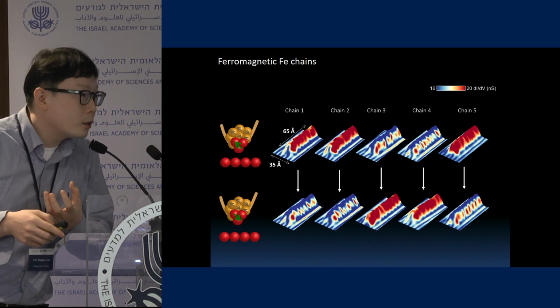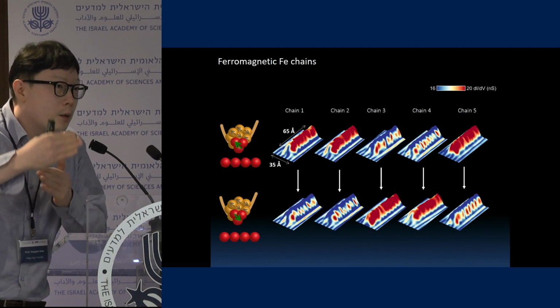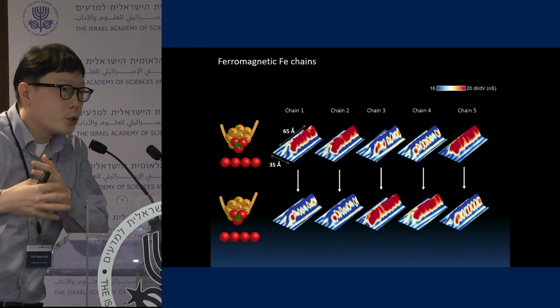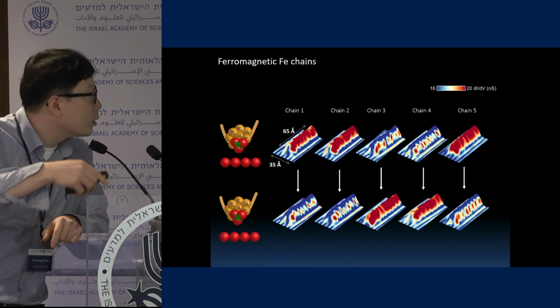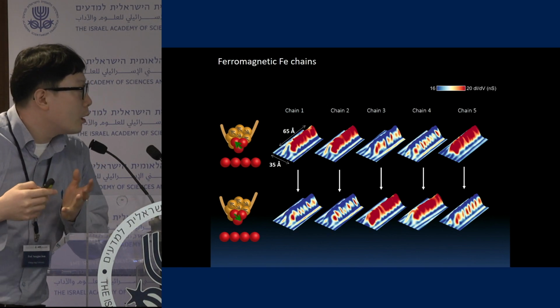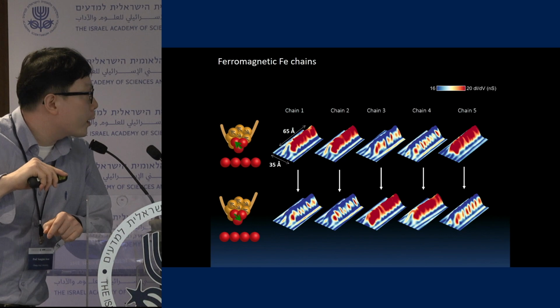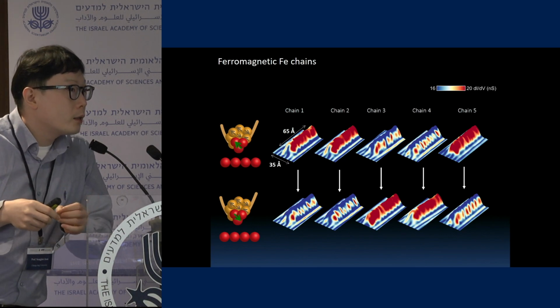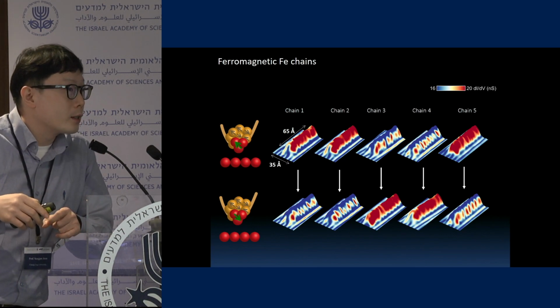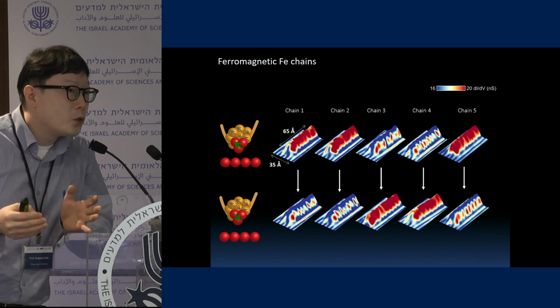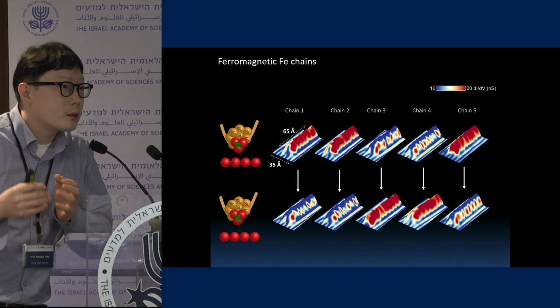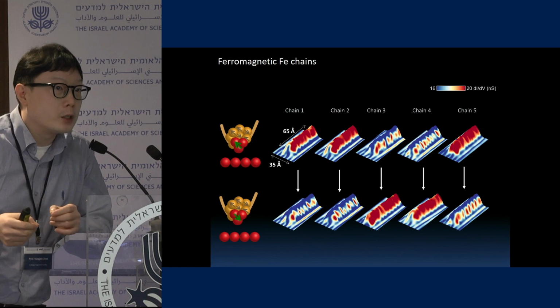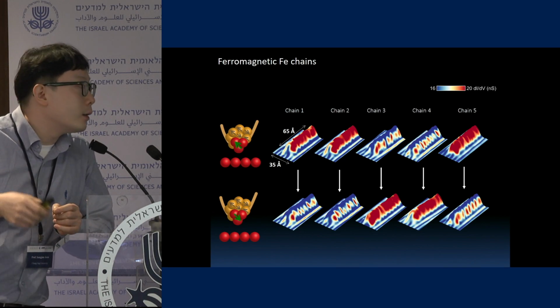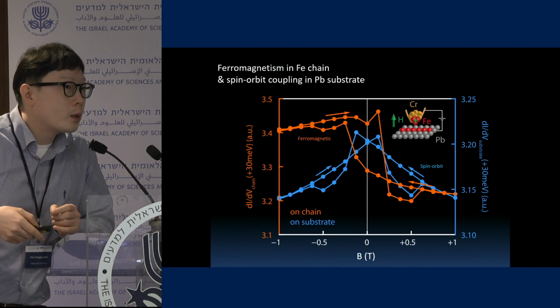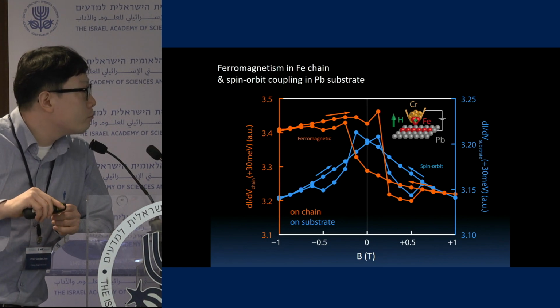So using scanning tunneling microscope, we try to look at some changing of magnetization in structure along the wire. But as we measure here many wires, many chains, it turns out that it is ferromagnetic systems. So it was very confusing at the moment. How can you get some zero end state with a ferromagnetic chain on a superconductor? And so we do more and more measurements on the system, and